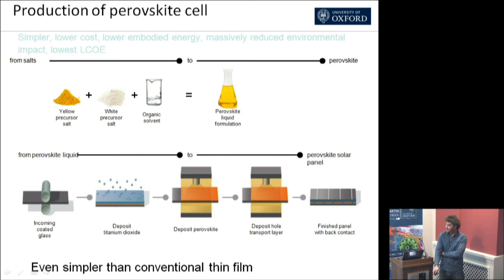So to now look at the manufacturing of this stuff, it's much, much simpler. You start from some precursors, some powders that are the salts. It's not table salt, but it's not too dissimilar and similarly priced. You mix it in a solvent, and that makes your precursor. So this is equivalent to the wafer stage in the silicon cell. And then basically we can coat these layers either by vapor deposition or via solution coating. We need about 5 layers in the stack to make the complete solar cell. So it should be much, much less expensive than silicon.